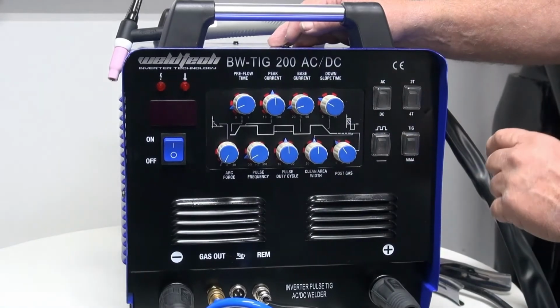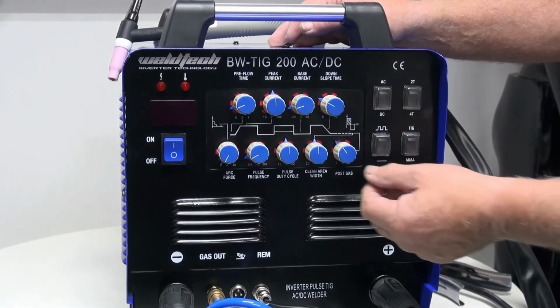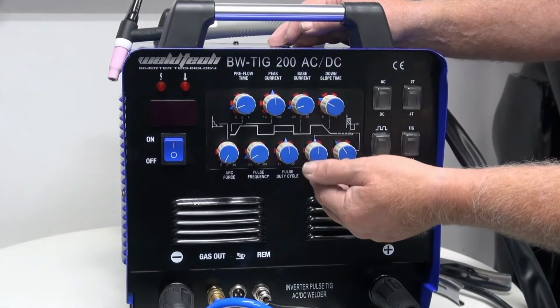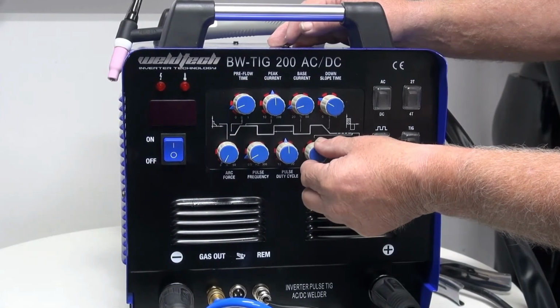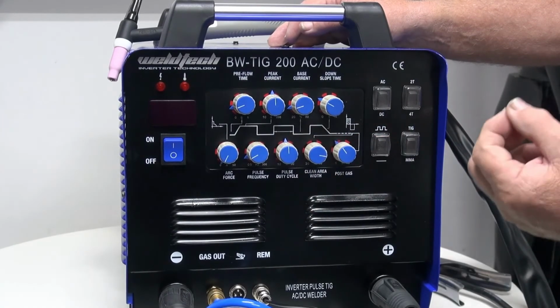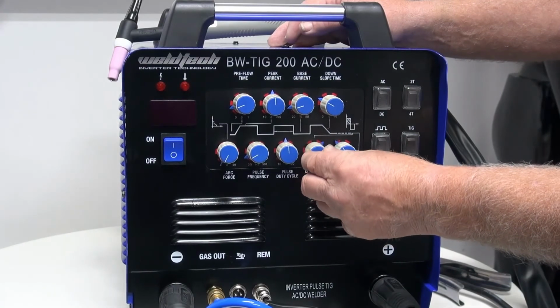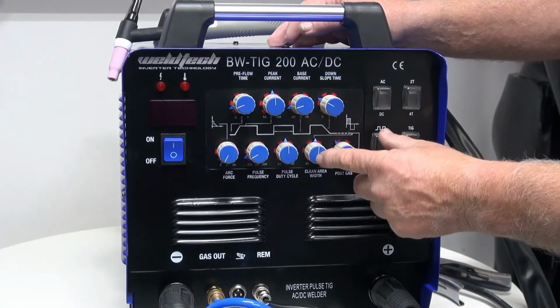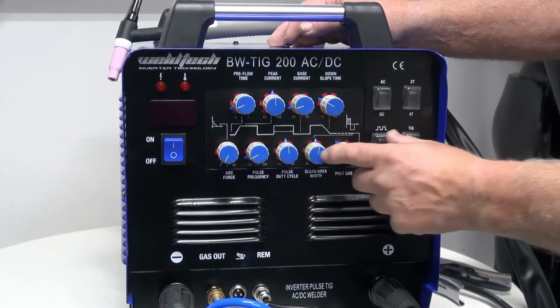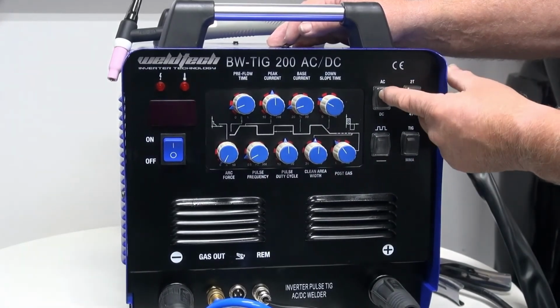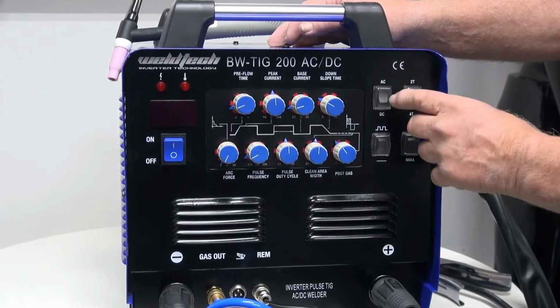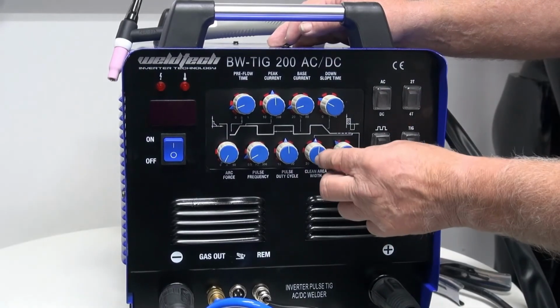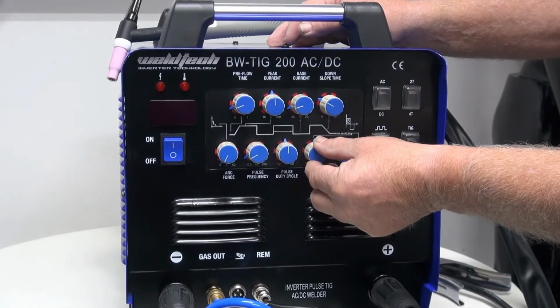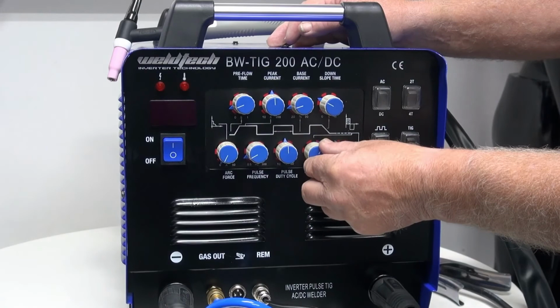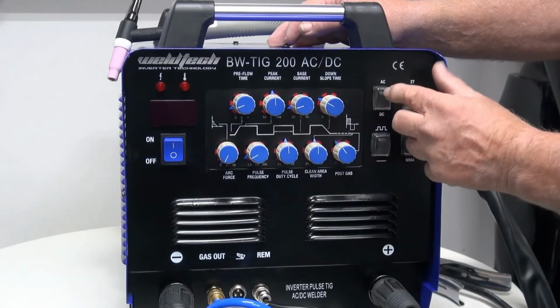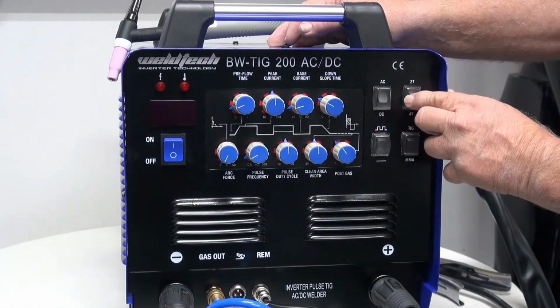Now, here's another tip. When you put a brand new tungsten in for aluminium, we want to be able to adjust it and get a nice ball on the end of the tungsten. I always wind that round to there, get the ball on my tungsten, and then turn it back. The other thing with the AC balance is that it only works when you have the switch up here switched into AC. When you have it in DC, it's always preferable to set it at 50-50. But when you're adjusting it, it will only adjust when you're in AC mode.